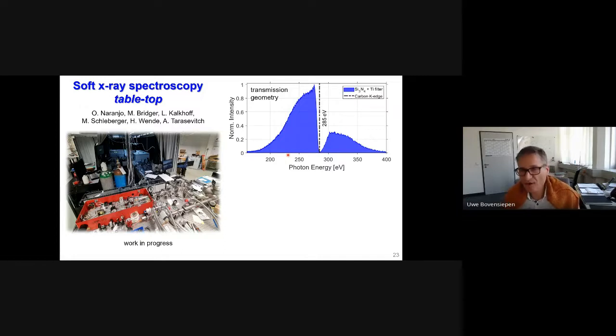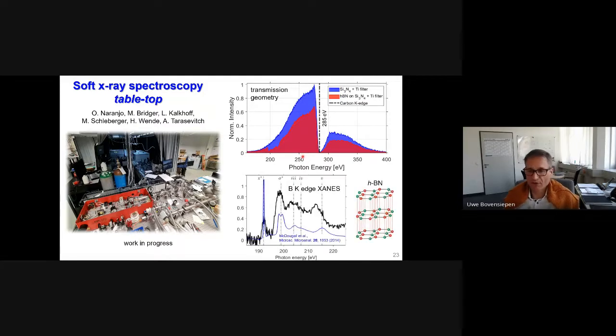Now we can simply add a sample, so to speak, as a filter, and we use here hexagonal boron nitride, and we see a pronounced change in this region here, and we can now, by normalizing, get out the proper absorption spectrum. The black line is what we measure, and we see here 1, 2, 3, 4, 5 signatures in this absorption. This is the absorption at the boron K edge in hexagonal boron nitride, which is a layered compound similar to graphite, but you have nitrogen and boron atoms in one layer, and we transmit here through a 90 nanometer thick sample, analyzing here the soft X-ray spectrum.